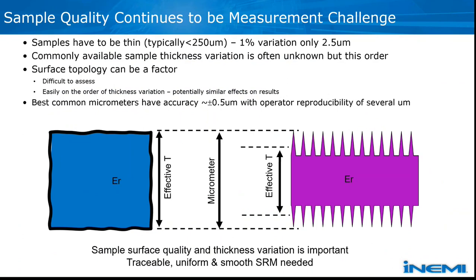I mentioned that sample quality is an issue, and it continues to be a measurement challenge. These samples are very thin because of the frequencies involved, so only a few microns of thickness variation can end up contributing percentages of results to the final answer. Commonly available material thicknesses have variations on the order of many microns, and it turns out to be very difficult to get super flat uniform samples. This is something we need to keep in mind, as sample quality and thickness issues are probably a leading area for improvement.